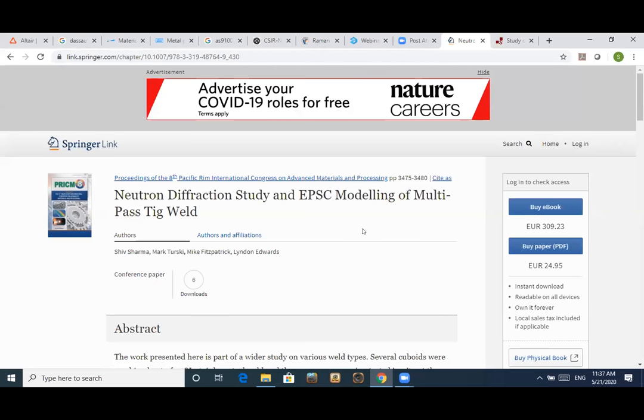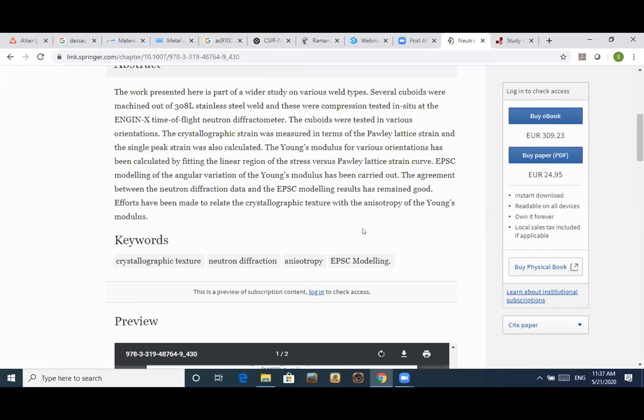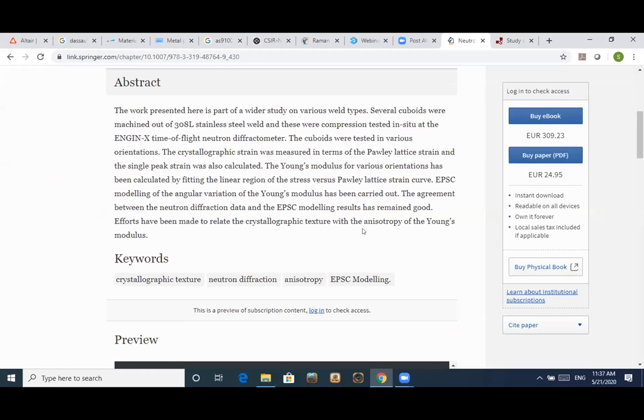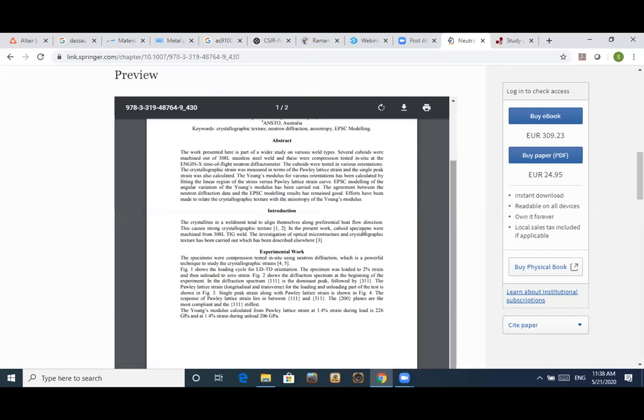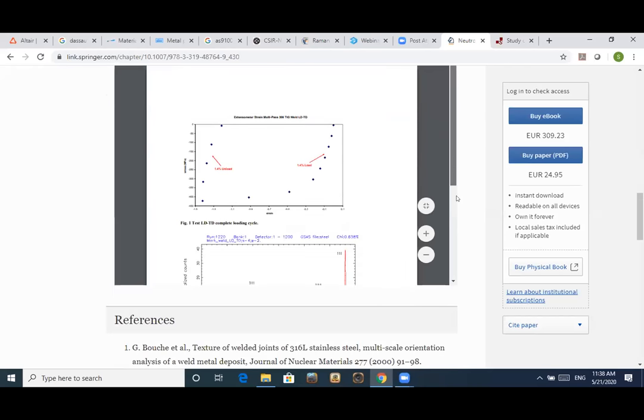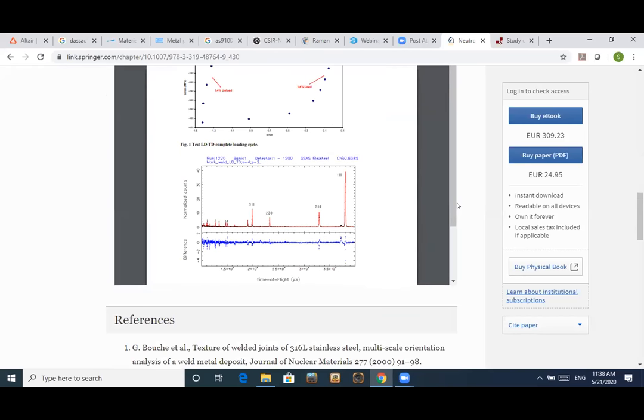Anisotropy, okay. Fine. Yeah, so we machined the tensile specimens from different orientations in the weld pad, as you showed. For example, you showed the tensile specimens which are parallel to the weld bead. In the same way, I machined in three different orientations. And then we did the neutron diffraction. We conducted in situ neutron diffraction, where the tensile specimen was being deformed in the engineering diffractometer, and the response of the crystallographic planes was recorded.